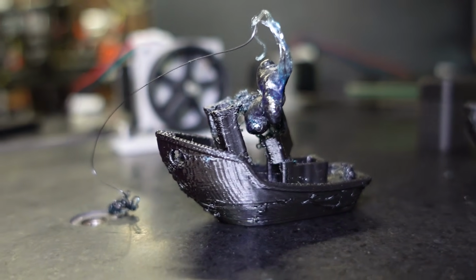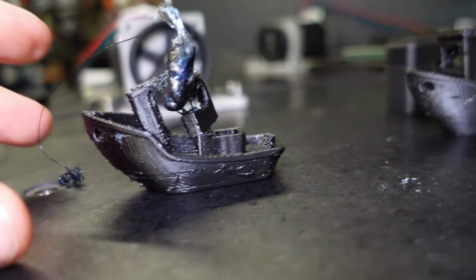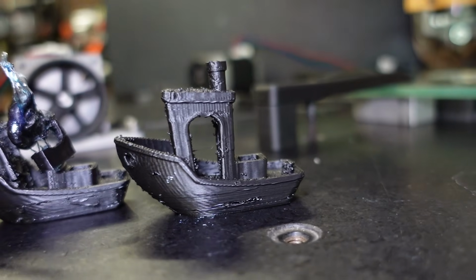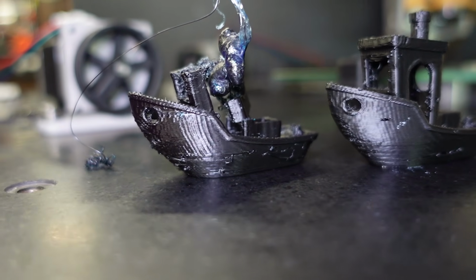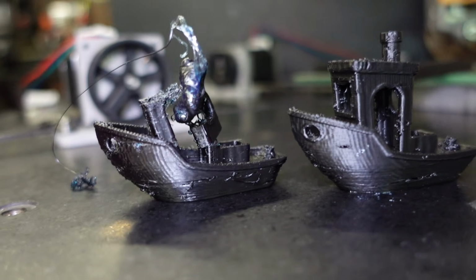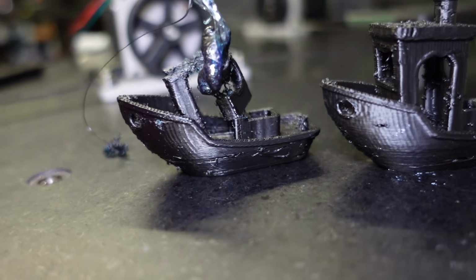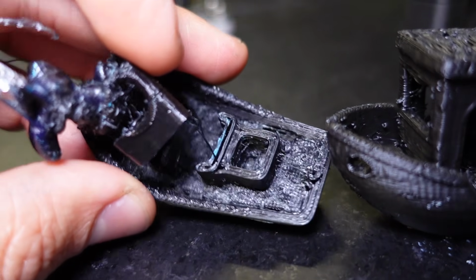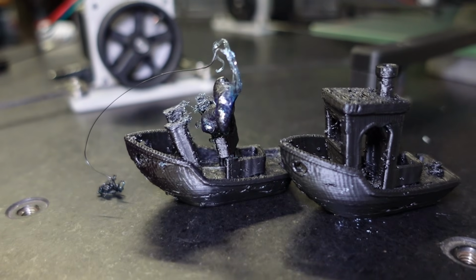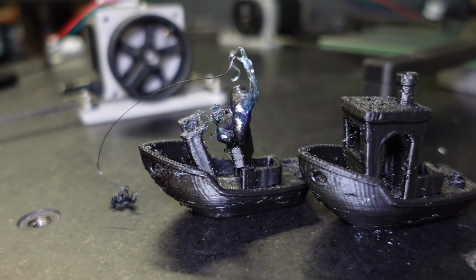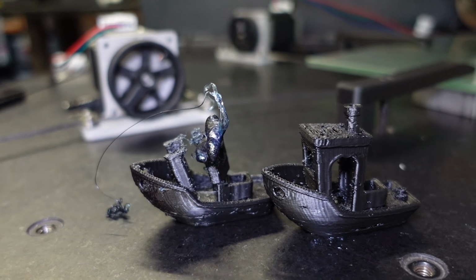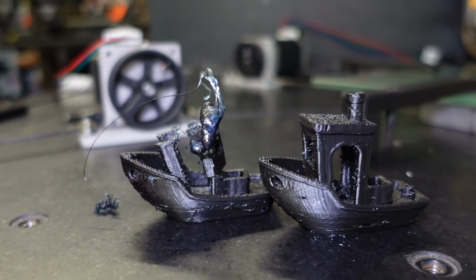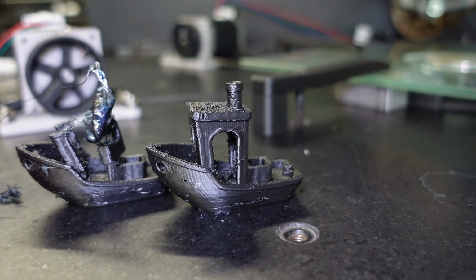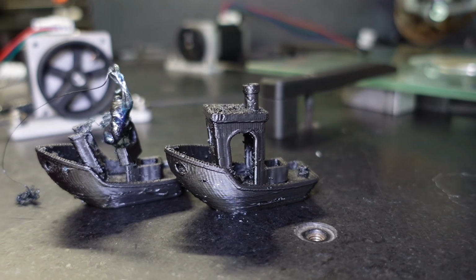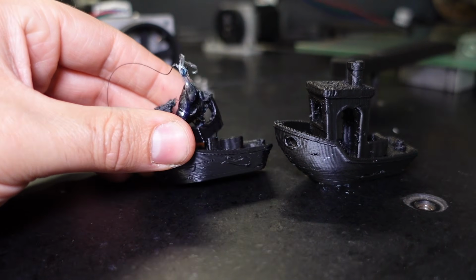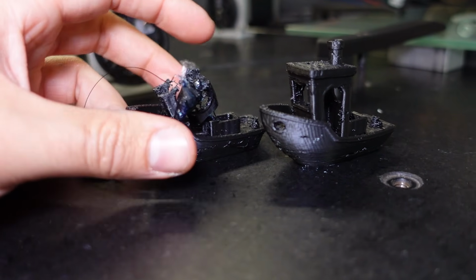Yeah, so this is what came out of here in comparison to the PETG graphene alone. And for anyone doubting that this is a co-extruded filament, there you can see it. That layer adhesion may become the issue here was as expected. PLA and PETG usually don't bond with each other very well. I've used that principle here a number of times as a support material, but then again, this seems to be quite solid. It detached here.